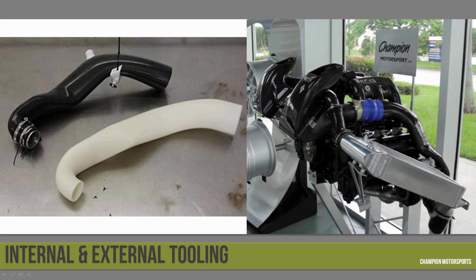You can see an example on the left, very oddly shaped piping. That's typical inside of an engine bay where you're working around other components and inside tight quarters. That core that you see there is an SR30 core and it's uncoated, but it has been sanded and deburred. And that's going to give them the best internal surface. These guys do use both internal and external tooling. I don't have a picture of the external here, but I did see it in the video. So we have an FDM core for the inside, and then the external, it looked like a fiberglass tool.